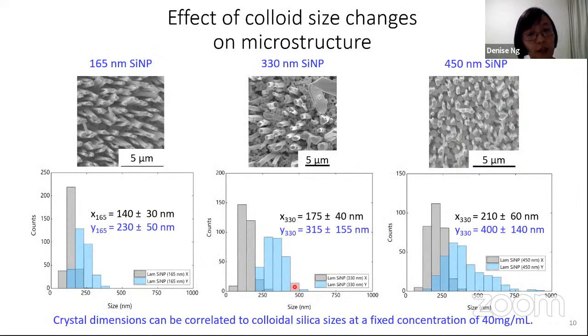Next, to study the effect of the colloid properties on the crystal attributes, we varied our colloidal silica sizes between 165 nanometers and 450 nanometers. And we observed that as we increase the colloidal silica size from 165 to 450 nanometers, we observe a corresponding increase in the crystal dimensions, for the X dimension from 140 to 210 nanometers, and for the Y dimension from 230 nanometers to 400 nanometers. Thus we can conclude that the crystal dimensions can be correlated to the colloidal silica sizes at a fixed concentration of 40 mg per ml. And this level of control, to the best of our knowledge, has not been reported in other work.